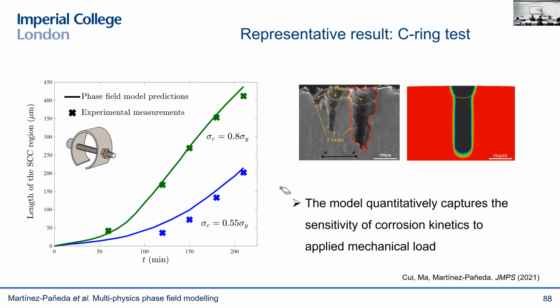And you can see here that we get a very good agreement with experiments, both, I would say, qualitatively and quantitatively, both in terms of the size of the corrosion defect for different applied loads, but also in terms of the corrosion morphology. So these two images are on the same scale, and you can see that we get a good agreement with experiments. We choose to model only one pit, but we can model multiple pits as well.